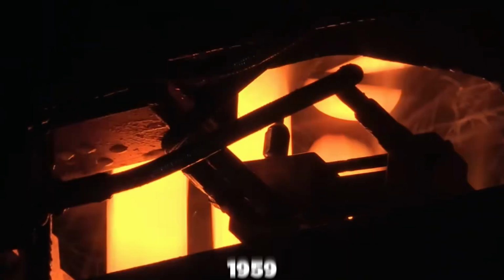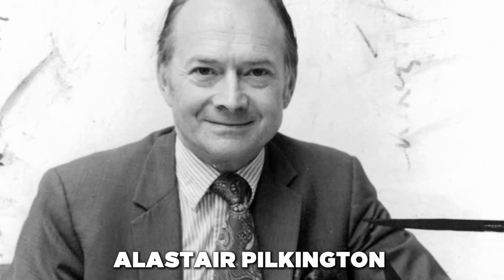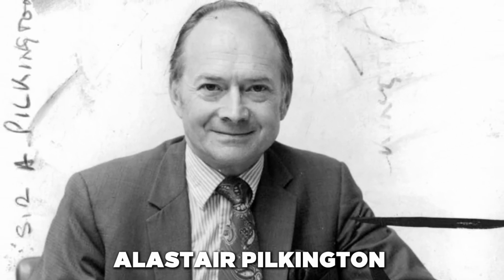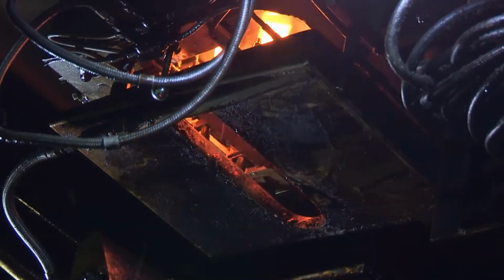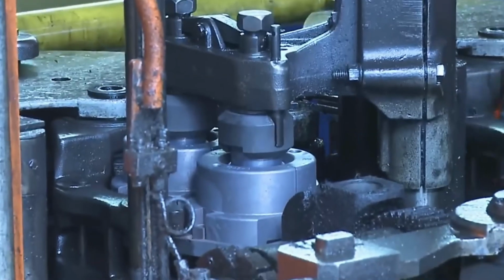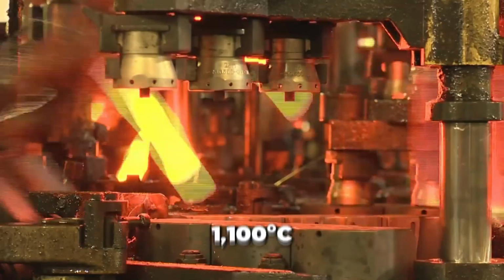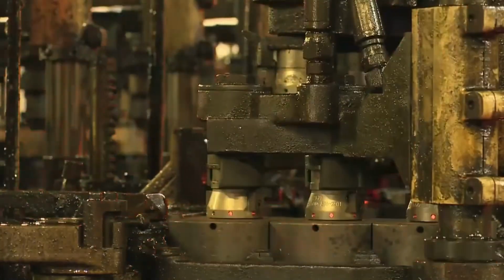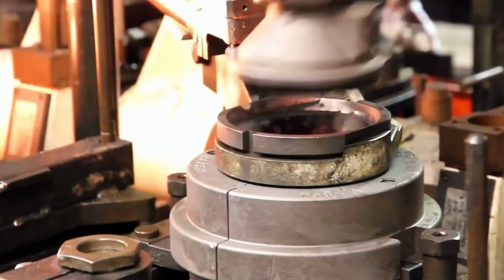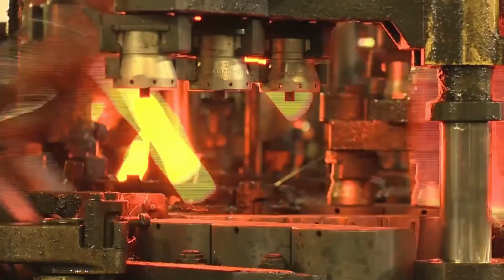Here's where the real innovation happens. In 1959, Alastair Pilkington invented something that changed everything, the float glass process. The molten glass is poured onto a bath of liquid tin heated to 1,100 degrees Celsius. Because glass is lighter than tin, it floats perfectly, creating mirror-smooth surfaces on both sides without any polishing.